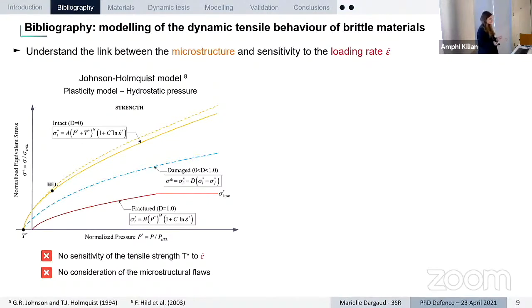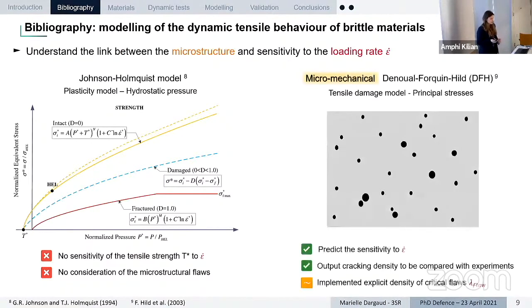For this reason, because we want to implement the microstructural defects, we are going to focus on micromechanical models. One possibility is to use the DFH model coming from Denoual-Forquin-Hild, which is a micromechanical model which can be used to model the tensile damage behavior in ceramic materials, in brittle materials.